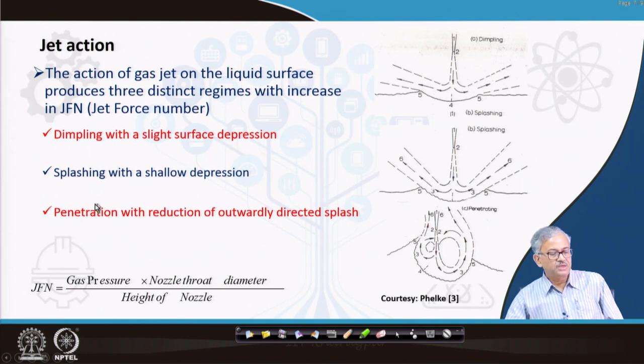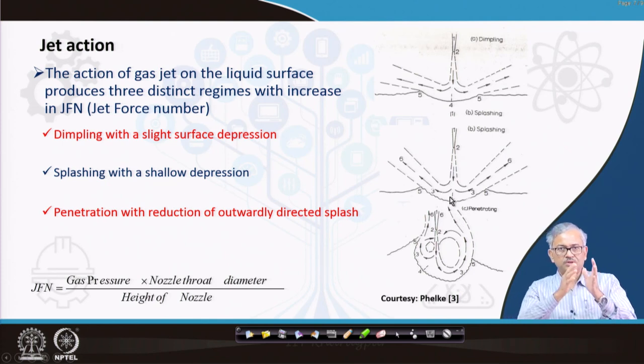In the case of penetration, the droplets are moving this way, so they are not splashing away. You are reducing the outwardly directed splash. Here they move a little, but finally they will hit the refractory wall and erode it. But in this case, all the droplets will move to the interior of the furnace, through the slag phase. That is penetration with reduction of outwardly directed splash.